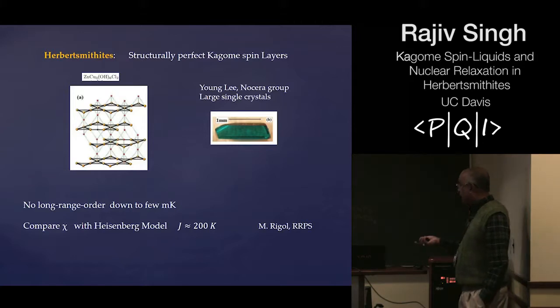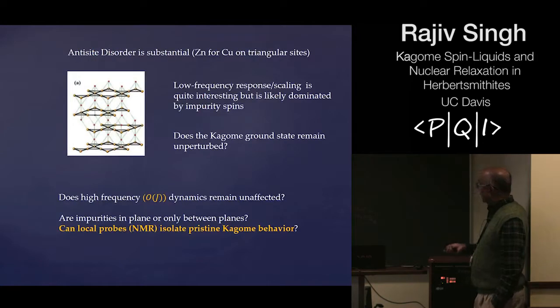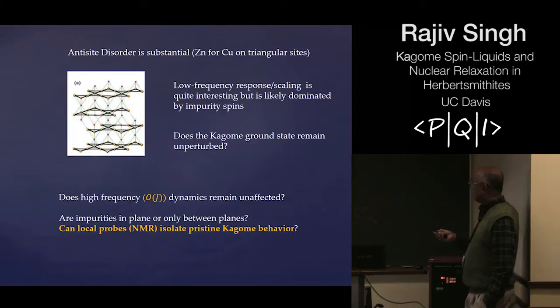So that is the first sign that possibly it could be a spin liquid. But unfortunately the one thing that is present in these materials is disorder. I mean, no materials are really free of disorder, but in this case there is a non-negligible amount of what I call anti-site disorder. That is, some of the zinc gets replaced by copper, and that means you have additional spins, and that means that it is hard to tell whether the system is gapless or not, because gapless excitations can come from these additional spins rather than from the Kagome system.